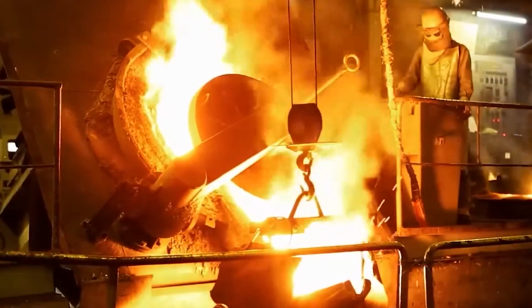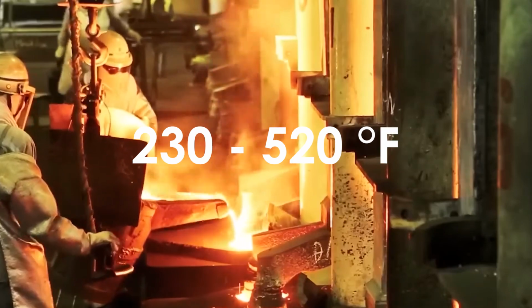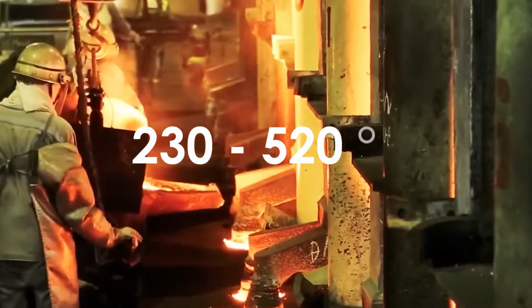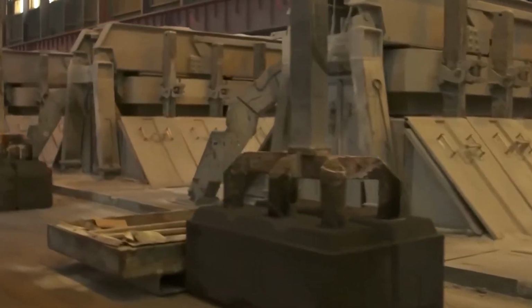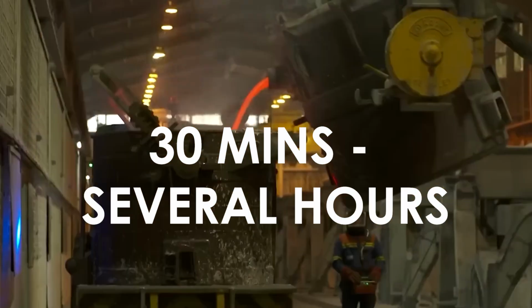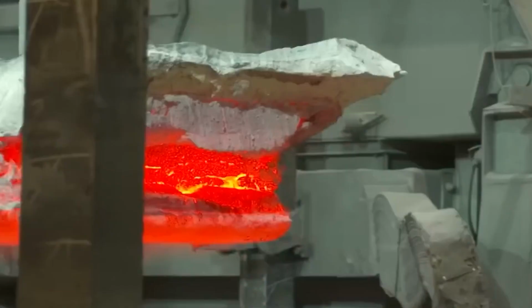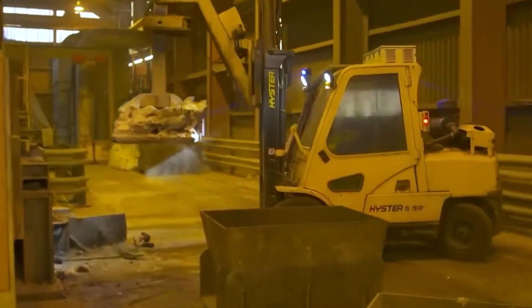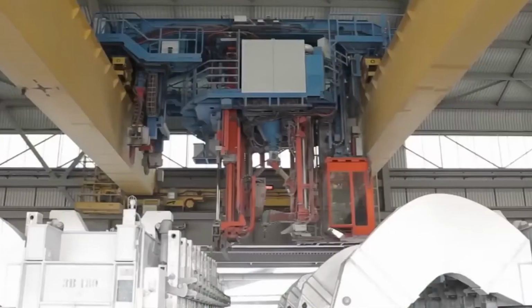Under 50 pounds per square inch of pressure, the slurry is heated to 230 to 520 degrees Fahrenheit for a duration of anywhere from 30 minutes to several hours. To make sure all the compounds containing aluminum dissolve, you can add more caustic soda. A sequence of flash tanks is used to lower the pressure and collect heat from the heated slurry, which is now a sodium aluminate solution. This heat can be recovered and utilized again during the refining process.